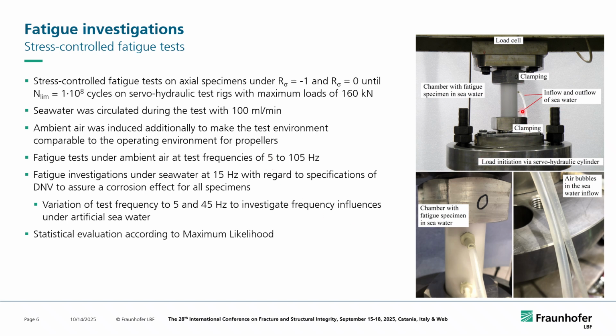And when we look here on the right side, we see the clamping, upper-lower clamping. We do not see the specimen in this case, but it's behind this chamber here. And we have then two smaller, flexible tubes that send in the seawater, also with some air bubbles. So with a pump, we induced regularly some ambient air to enhance the corrosive effect, and simulating that the propeller and the material is partly in air and partly in the water, depending also on the payload that is in the vessel itself.